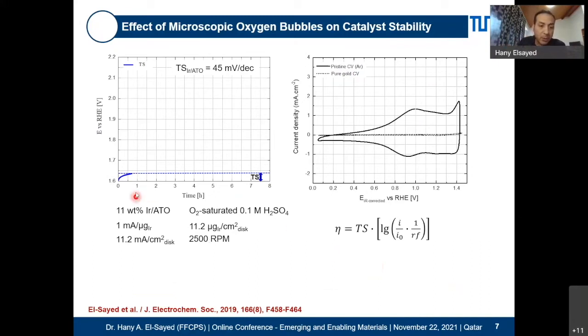And you can see here that we applied a constant current using our iridium ATO catalyst. It's homemade, and we allowed the potential to increase by what is equivalent to one Tafel slope. Tafel slope in this case is 45 millivolts. And when the potential increases by 1 Tafel slope, this should correspond to a degradation of the catalyst surface area by 90%, at least 90%.